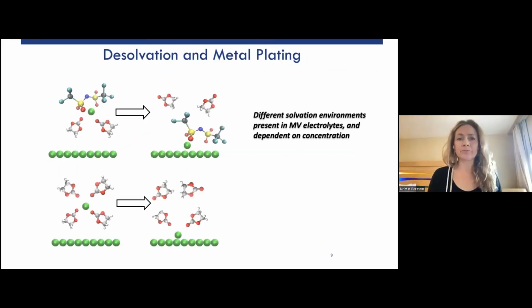Well, when you're desolvating or plating your electrolyte on the hopefully magnesium metal, in normal electrolytes, you assume something like the lower bottom picture, where lithium comes solvated by the solvent and it desolvates and nicely plates when it gets one electron. But in the magnesium case now, if your delivery vehicle are these majority contact ion pairs, you would expect the solvent to desolvate first because it isn't electrostatically bound to the magnesium as TFSI is, which is like a 2+ and a 1- interaction. It should be stronger. So we're expecting that the delivery vehicle at metal plating for multivalent systems, if your majority species is a contact ion pair, will be quite different.